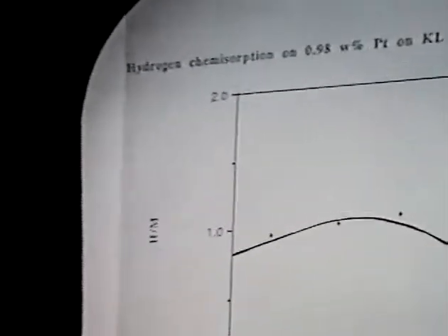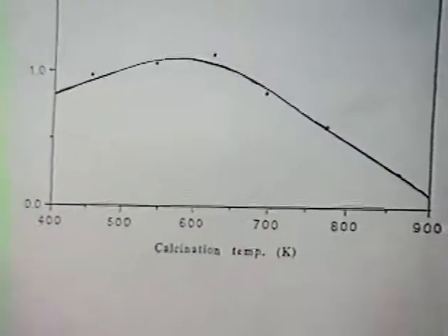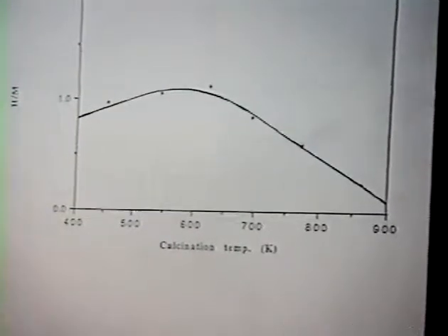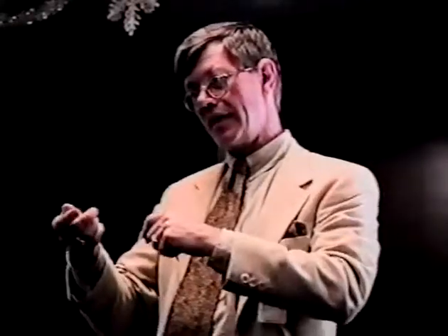But here's an example where it was ion exchange from the platinum amine to make about a 1% loading of platinum, and then it's back exchanged. The reason you back exchange: if you ion exchange the platinum in, you've got a platinum 2+ cation, and then you reduce it. For every platinum cation in there, when you reduce it to metal, by stoichiometry, you have to put 2 protons somewhere. And so you actually build in acidity by the ion exchange and reduction. So to get rid of that residual acidity, you back exchange after you reduce the metal, the protons for potassium, to get back to a more basic catalyst.